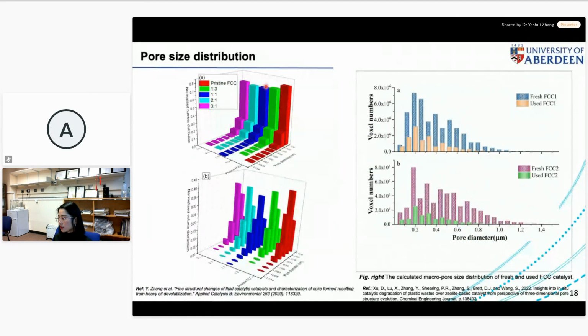Well, it's quite normal for researchers who are working on catalysis. We normally use a nitrogen adsorption and desorption method to quantify the pore distribution. But that is for batch analysis. We're using this X-ray CT to only look at a single catalyst particle. We can still count how many pores there are in different sizes and plot these pore distributions.